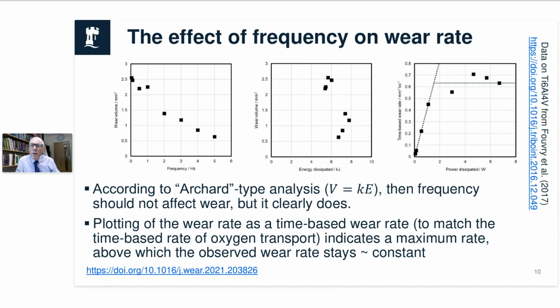What we did is actually we looked at the wear rate. So we simply took that middle figure and divided it by time. If you divide one by time, you've got to do the other one by time. You then have power dissipated. And what we found then was that the wear rate stifled. As we increased the power, the wear rate stifled. And so we ended up with that horizontal line across the top. And we said that was a time-based wear rate, not a per joule of energy. This is now time-based. And we said that we believe that is to do with oxygen ingress, a limited rate to do with how fast the oxygen could get into the contact.